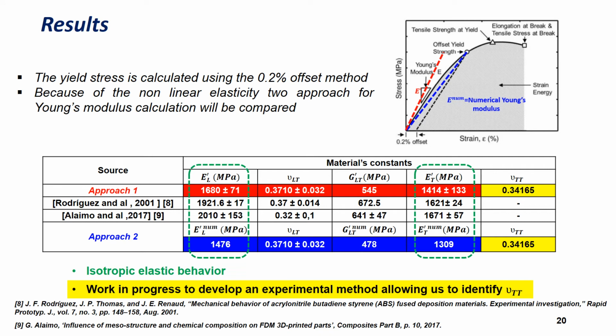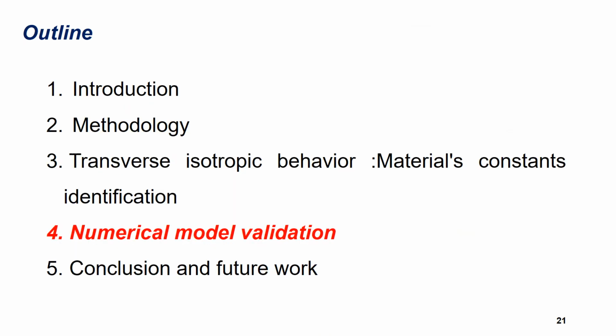For the last constant, we are working on an experimental setup to allow us to calculate it. The idea is to use a digital image correlation setup with two cameras that gives an estimation of the off-plane displacement. Next step is to check the validity of the identified elastic constants. For that, we will use the local reference assignment to reproduce the deposition trajectory into the model.